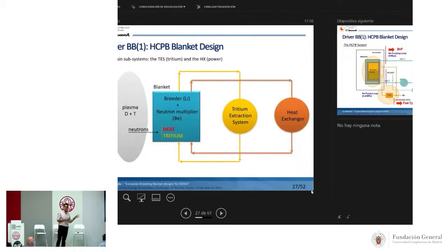And what is important here, I go to the next slide, is this one. I go back to the schematics of the breeding blanket. We need a tritium extraction system and a heat exchanger. For the HCPB, this is quite important because how can we extract the tritium? Because we have the pebbles of lithium, the neutrons impact the pebbles, we produce tritium inside the pebbles, and we need to extract this tritium from the blanket. So for that, we use an additional loop of helium, which is used as a purge gas. Okay? It's a carrier, a gas which goes through all the pebbles and carries all the tritium to the tritium extraction system. And additionally, we have another loop of helium to extract the heat.